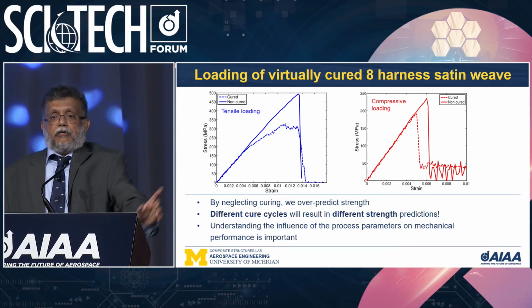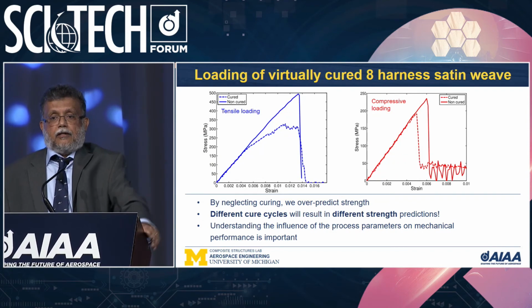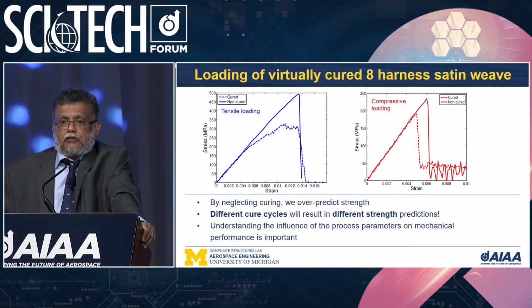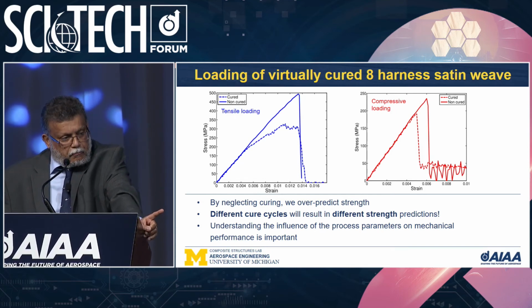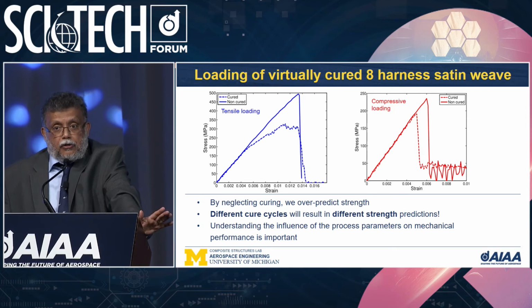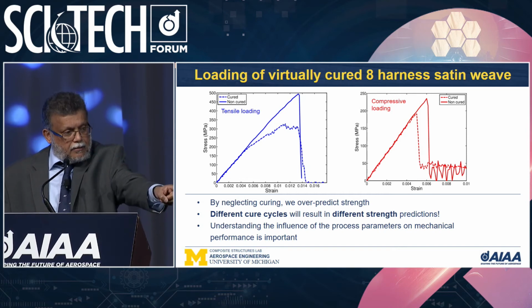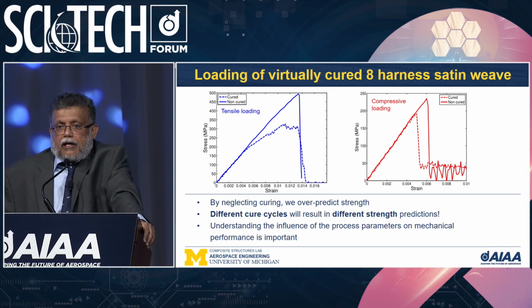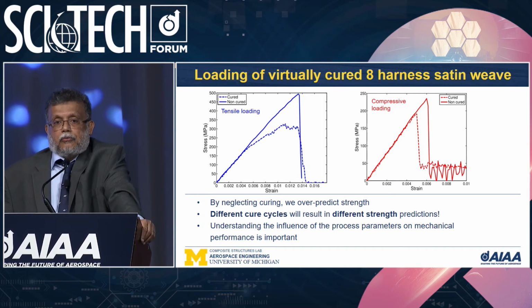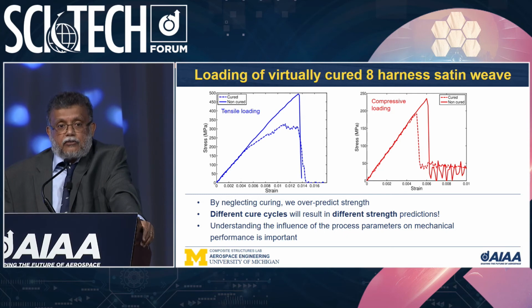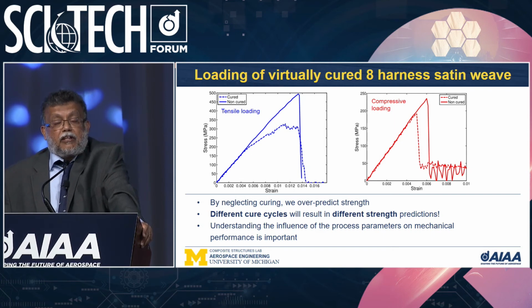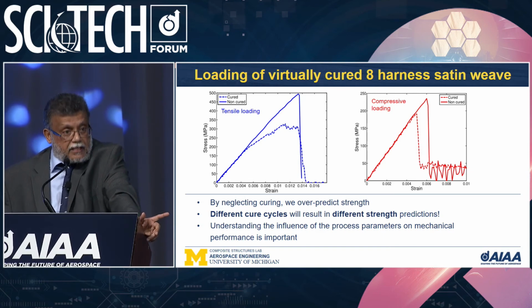What's more important is to realize that if you ignore the cure cycle, you can get misleading values for the strengths. You can see here in this plot where we did not cure and did not include any thermal stresses, and we did virtual tensile tests. If you include the curing stresses, you get a lower value because there are residual stresses in the matrix. Similarly, we show the same for compression. So different cure cycles will result in different strength predictions as well when you change the cure cycle. This is very important to understand for textiles.